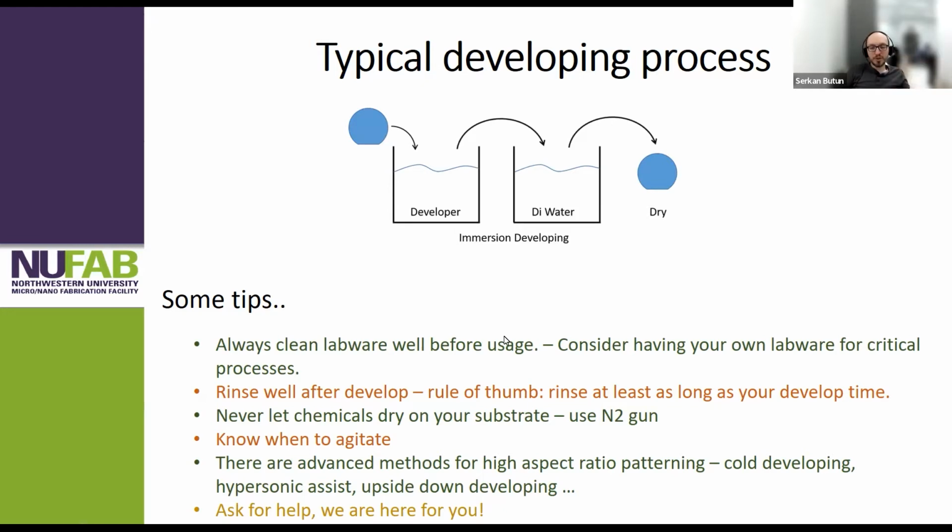So that will cause a lot of trouble. Generally, rule of thumb is you need to rinse at least as long as you develop, right? So if you're doing 1 minute developing, you need at least 1 minute rinsing. And when users usually ask me, I jokingly say, just rinse it as long as you think it's enough, and then double it, right? So there's no harm rinsing it too much.